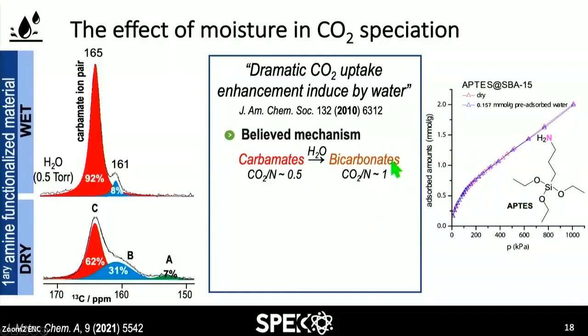But if we observe our NMR spectra, and these are carbon quantitative NMR, okay? If you look at the dry, under dry conditions, and let me go back a little bit, one of the reasons why it is so important to pack the rotor in a controlled atmosphere is that this species over here, that we call A, even with the slightest amount of water, 0.5 torrs, it really disappears. So if you don't do it in these conditions, you will never catch it, you will never observe it.